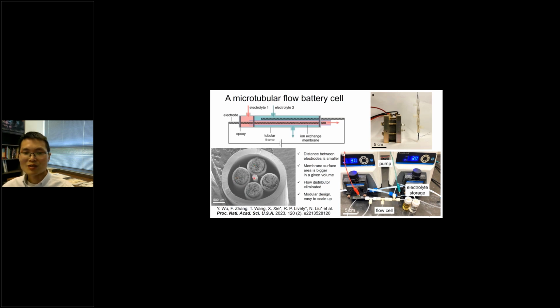And the distance between electrodes becomes very small, and this is very good for the kinetics. And also the membrane surface area in a given volume of the device is very large. And this is good because you can shrink the power module to very small, reduce the footprint, and reduce the cost. And you eliminate the flow distributor, and this will further reduce the cost.